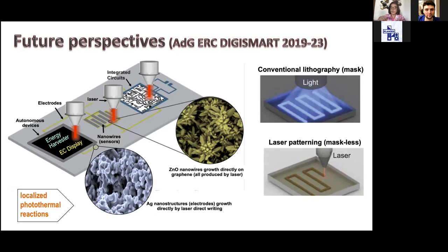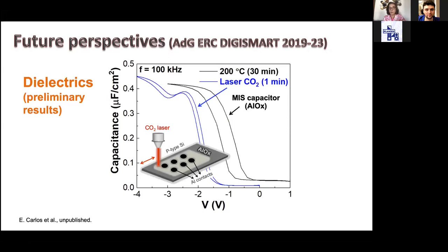So by using a solution approach in combination with the laser process, it is possible to exploit the energy of the laser radiation to promote all the photochemical reactions within the material and simultaneously to pattern the devices. So this is more or less what we are doing within this project. We already have some preliminary results.